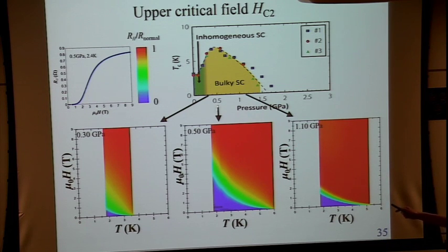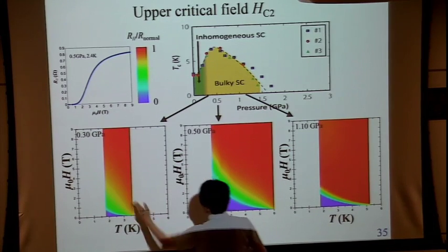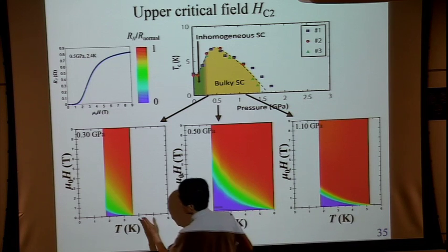However, if you apply pressure further, this zero resistivity region is extended and the normal state is pushed to higher fields. And at high temperature regions, the conventional highly correlated metal is realized. In this case, the transition from the superconducting state to the normal state is very clear, very sharp. It's a conventional behavior. So in such a case, it's not so straightforward to determine the upper critical field. Upper critical field characterizes the magnetic field which kills the superconductivity. But we define the critical field at the point where the resistivity is 80% recovered.